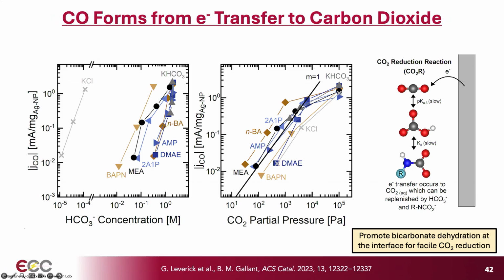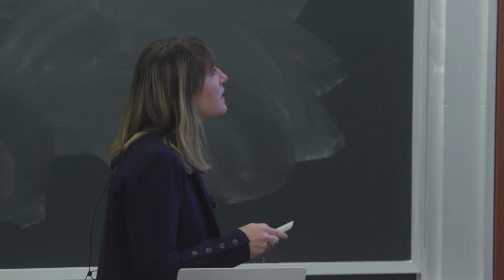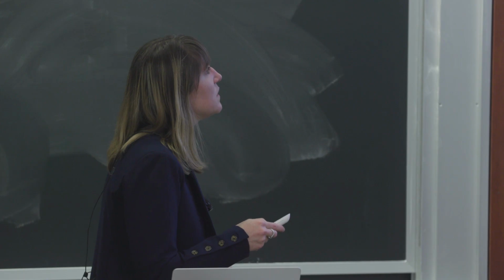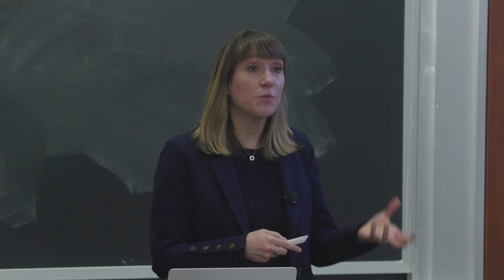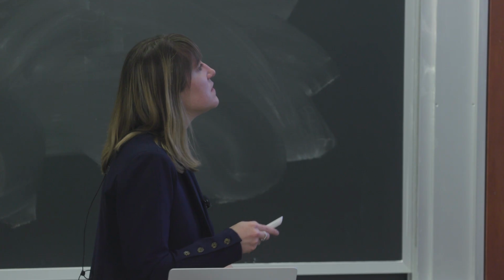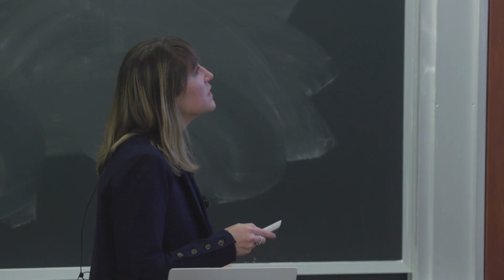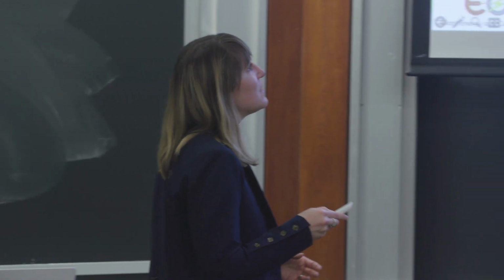If you look at a graph of the reaction rate forming CO as a function of the bicarbonate concentration, you'll see we do see a pretty good correlation for our different amine systems. But this cannot fully explain this trend because we also get very high CO production rates in a system that doesn't have amines in it, but the bicarbonate concentration is several orders of magnitude lower. So what we wound up finding is that really the tightest correlation across all systems universally is between the CO2 partial pressure, which is like a proxy for the dissolved CO2 in the system, and the CO selectivity. So what we concluded is that it's really actually the dissolved CO2 in the system that is receiving the electron and kind of active for CO2 conversion.